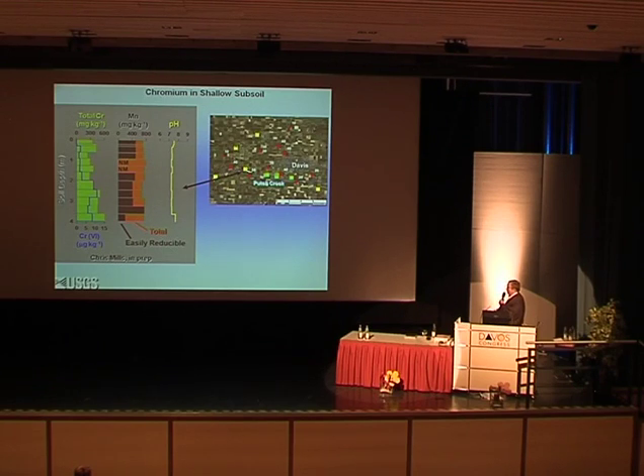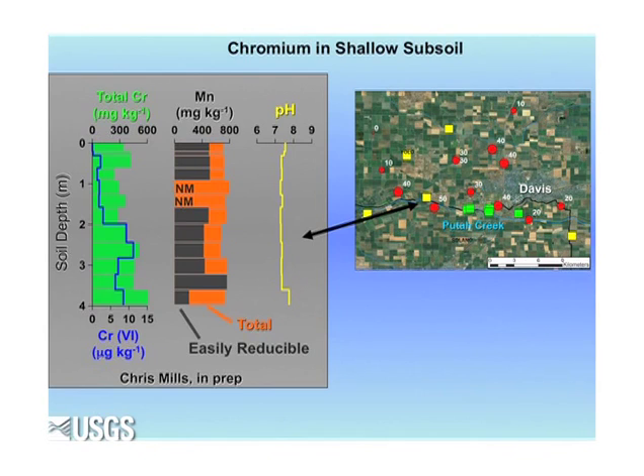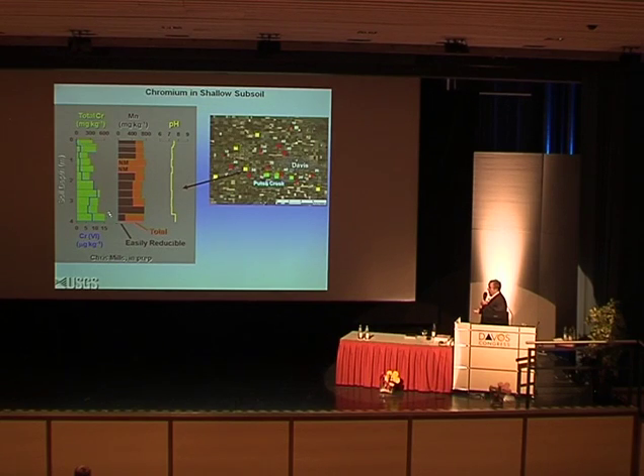We have taken a number of auger holes whose depth is of several meters, in this case 4 meters. Deeper drill holes, which I'm not showing data for here, are located here. Putah Creek, which I mentioned, is there. The town of Davis is here, and UC Davis is sort of there. What you see in this chemical data from the auger hole, in green, is total chromium. Total chromium relates to the upper graph and is extremely high, up to 600 milligrams per kilogram, remembering that the continental average for the U.S. is a number like 40. On the other hand, total chromium 6 is very low, micrograms per kilogram.